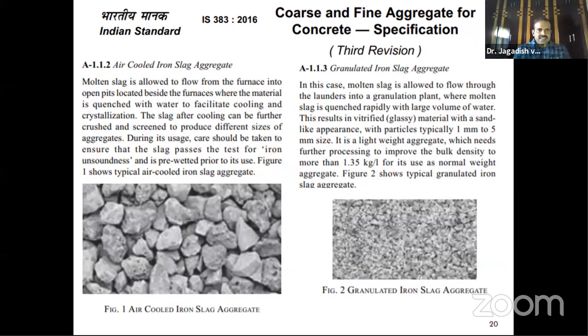In the first case, it is quenching with water and then cooling and crystallizing. In the second case, granulated iron slag aggregate, it is quenching rapidly with large volumes of water. So this is the difference between the air-cooled iron slag aggregate and the granulated iron slag aggregate.